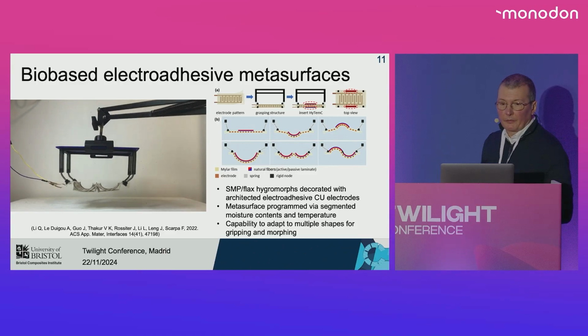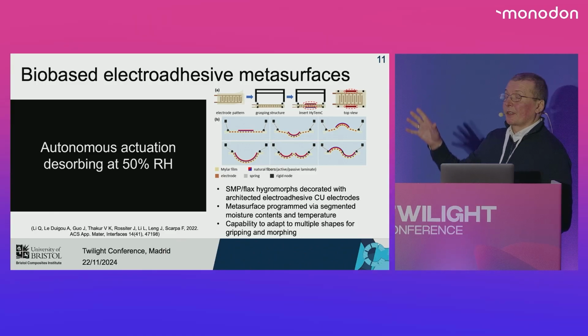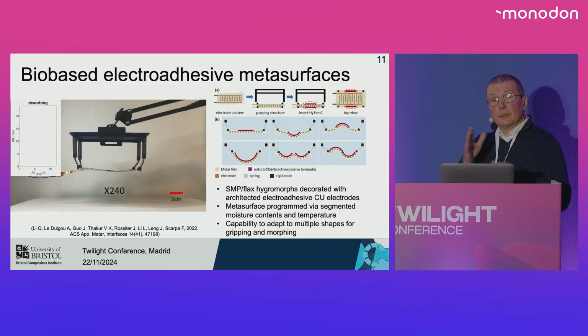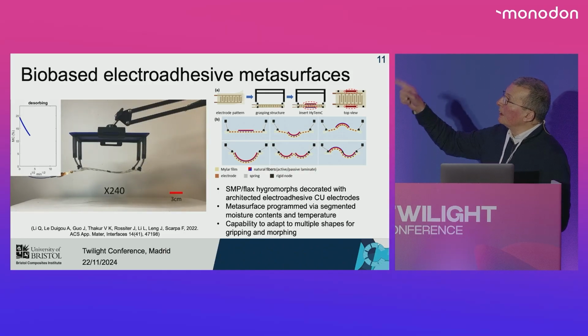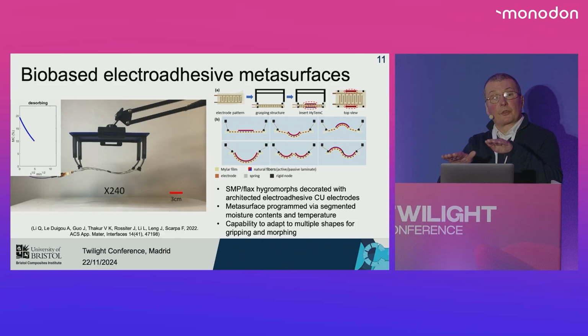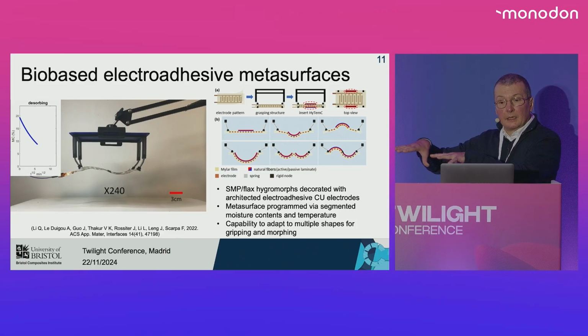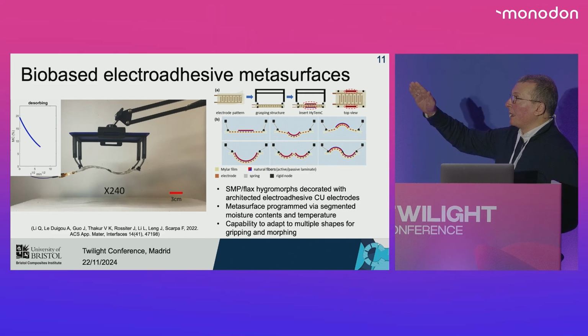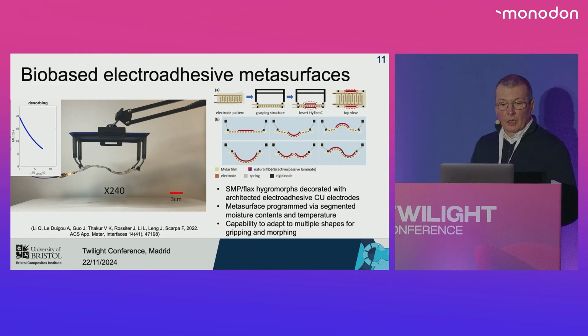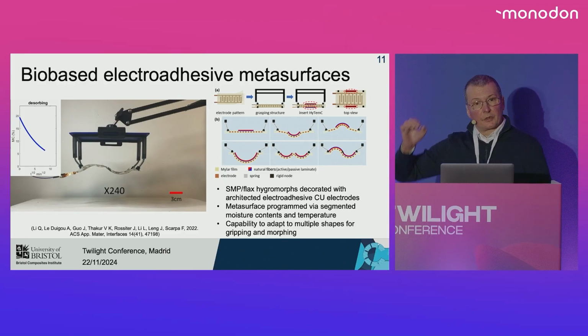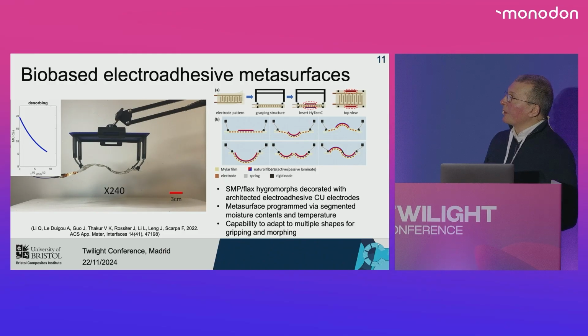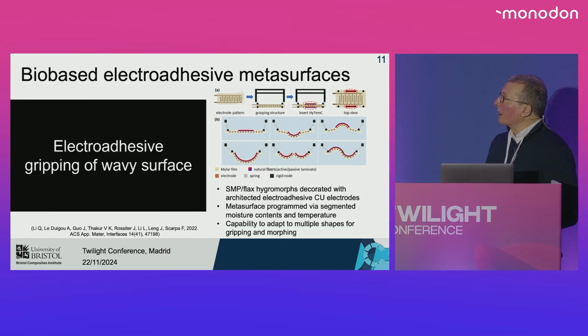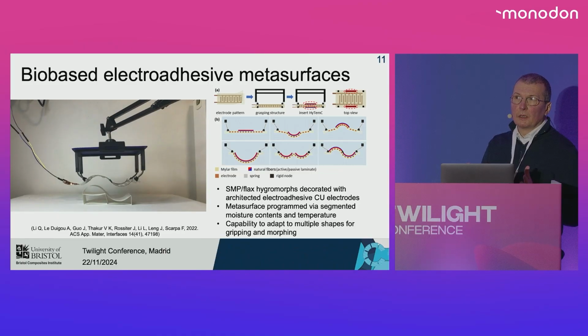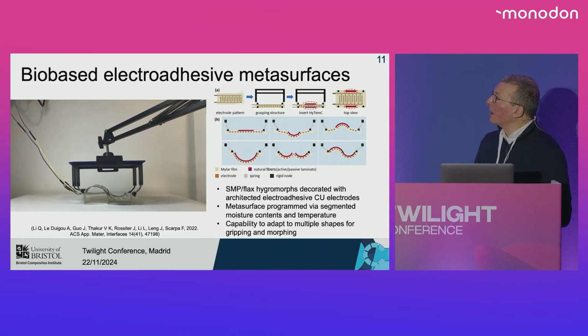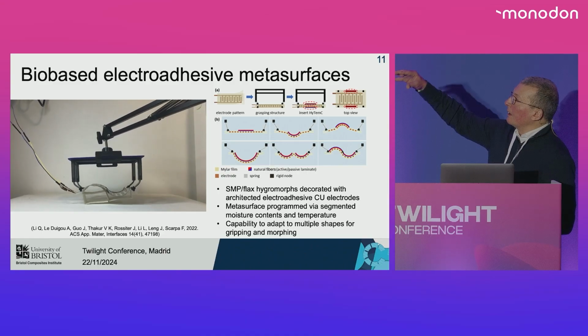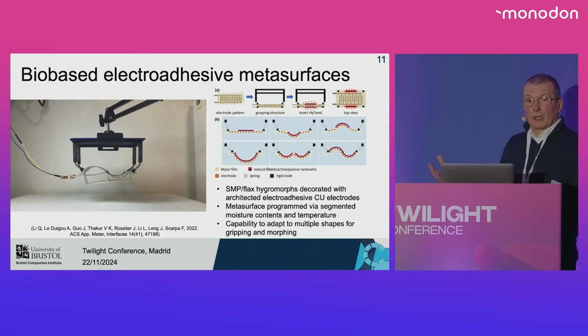very complex surface. Exactly the same type of metasurface can do also the double concave type of shape, because in that case, in desorption, because of the different type of architecture in a different set of patches, we can obtain now this type of double concave configuration, always with the same relative humidity in desorption. We start then to activate the electroadhesive copper films, talking about between 3.5 and 4 kilovolts per millimeter. And then we can grab a different, but yet complex surface.